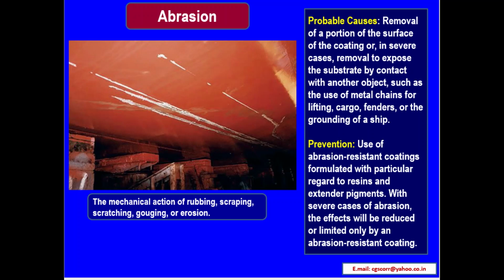First one is abrasion. The figure on the left top side gives you a picturesque view of the abrasion on a coated surface in a ship hull. The mechanical action of rubbing, scraping, scratching, gouging or erosion. Probable causes: removal of a portion of the surface of the coating, or in severe cases, removal to expose the substrate by contact with another object, such as the use of metal chains for lifting, cargo, fenders or grounding of a ship. Prevention: use of abrasion resistant coatings formulated with particular regard to resins and extender pigments. With severe cases of abrasion, the effects will be reduced or limited only by an abrasion resistant coating.